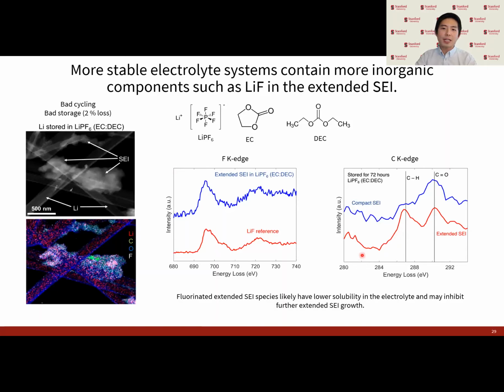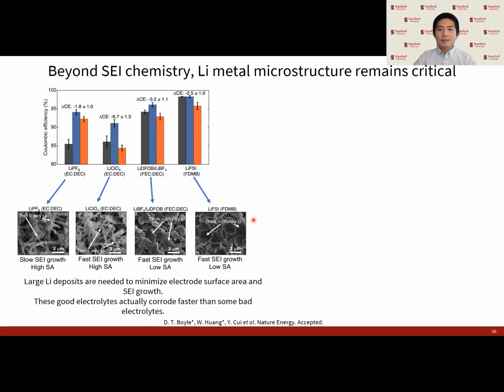And from this, it appears that the presence of this fluorinated species helps reduce the runaway solvent decomposition that we saw previously in the perchlorate case. So even though we showed previously that the lithium fluoride is very dilute and probably doesn't impact lithium metal cycling significantly, it does still appear to benefit the storage stability of lithium metal. And so from all of this, it appears that these subtle SEI chemistry changes can significantly impact the storage performance of these different lithium metal systems, mainly by affecting the rates or the degree of the SEI growth.